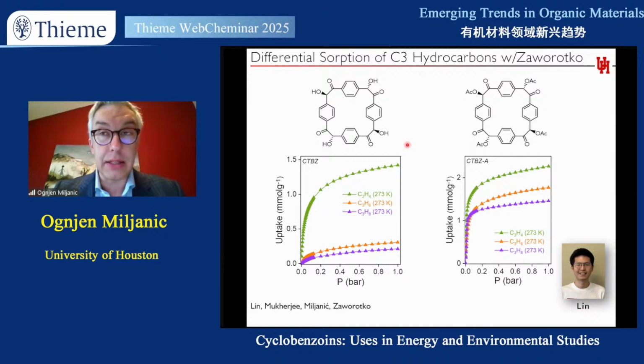This current separation is done through cryogenic distillation, which is very energy consuming. And so what we see here, acetylated cyclotetrabenzoin, and still selectivity, but not nearly as high in the acetylated molecule. And through a combination of molecular dynamic simulations and powder X-ray diffraction at a synchrotron with these guests included, we have shown two things. One, while the molecule on the right has those square-shaped pores and the diamond-shaped ones, which I've shown you below, the square-shaped pores are selective, the diamond-shaped ones are not. And because of that, overall selectivity is eroded in these bindings.